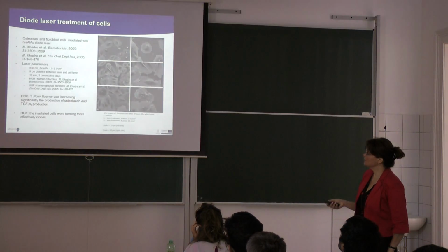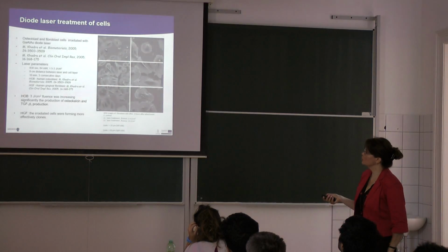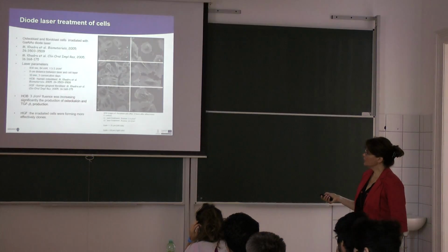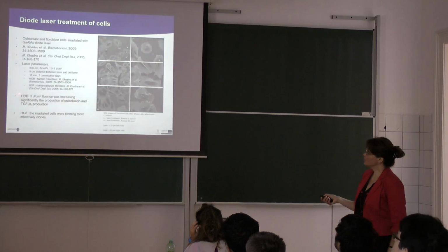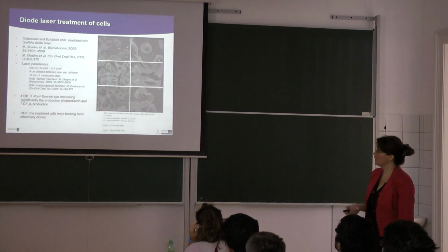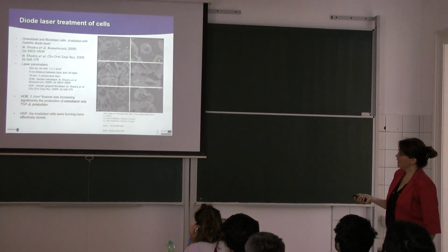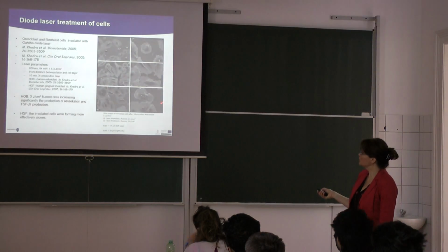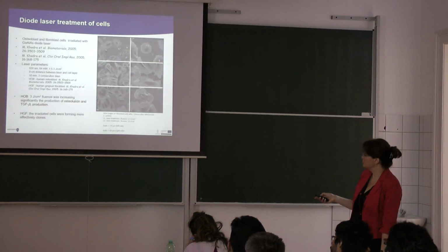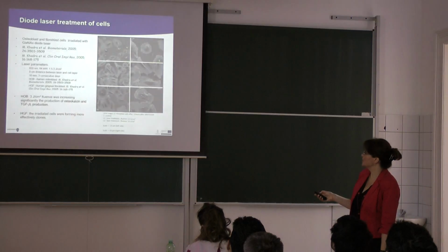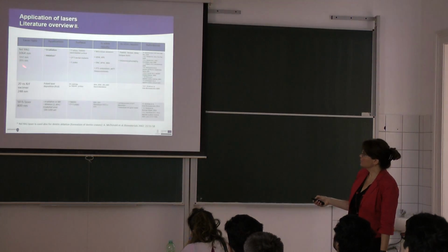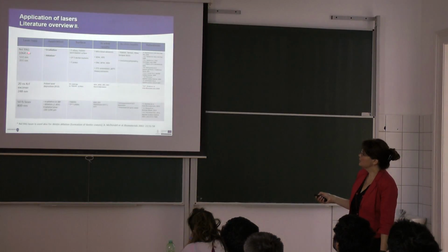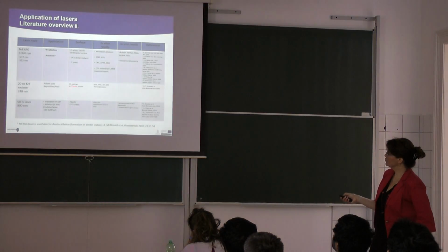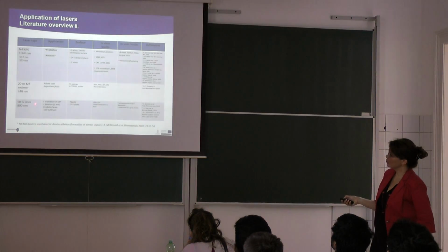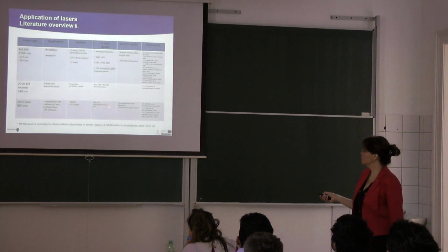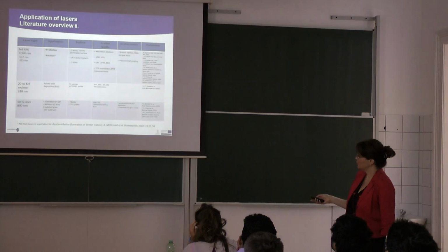So the diode laser treatment of the cells was used by Khadra and his co-workers, and they have published two articles also. These are the laser parameters, and they really have shown that human osteoblasts increased, and the production of osteocalcin and TGF-beta was enhanced, and also the irradiated cells were closing the wound more effectively. You can see nice microscopic slides about that, and this was a very positive treatment of the cells. Then if you go further, the neodymium laser, which uses 1064 nanometers, is used; less used is the krypton fluoride excimer laser, with just one article. And then you have the very short laser impulses, 50 femtosecond lasers, which are also used for treatment of Ti-6Al-4V and CP titanium plates.